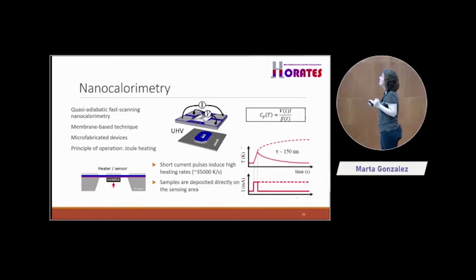But the good thing about platinum is that its resistance depends quite linearly on temperature. Okay, so if you represent R, resistance, versus temperature, you get something that is quite straight. So if we know the resistance of the platinum during the treatment, we have access to the temperature. How can we get the resistance? Well, measuring the voltage. You know the intensity, you measure the voltage, you know the resistance, that's it. It's that easy, okay? So what we do is deposit our samples just on this platinum circuit, and provide an intensity pulse here, a very short one, and this is like the temperature profile that will follow the platinum without sample.